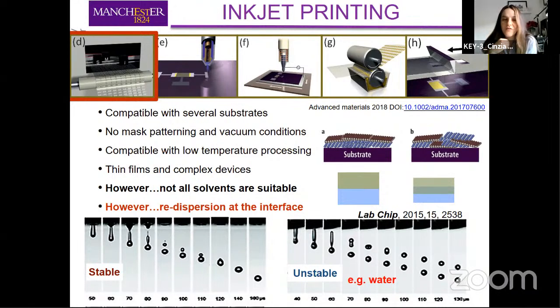In addition to that, we also have another issue to remember, and this is related to the fabrication of vertical devices. It's very easy to use inkjet printing when you want to make in-plane devices, but for vertical devices, there is a problem we need to take into account, which is very well known in the community. When we print one material on top of the other, the two materials will tend to redisperse at the interface. And this is obviously very bad in terms of device fabrication, because devices need very well defined interfaces. So we cannot really produce devices if we are not able to control the interface between the different materials. This will affect the reproducibility and the performance of the device. So this problem needs to be mitigated somehow.